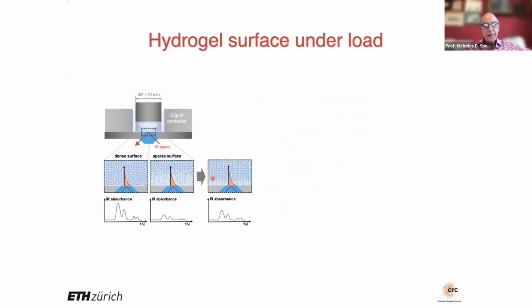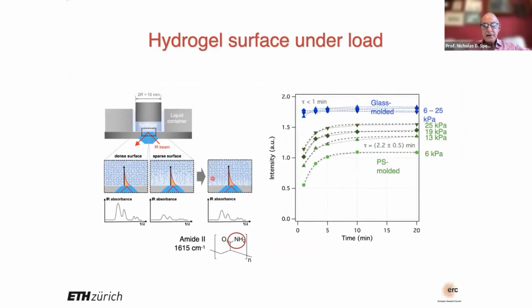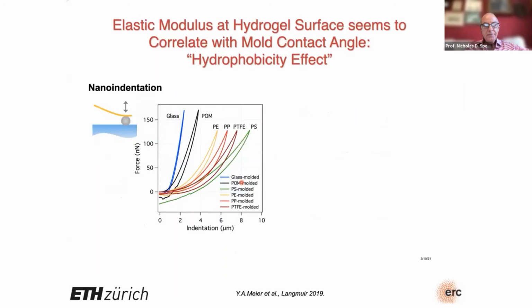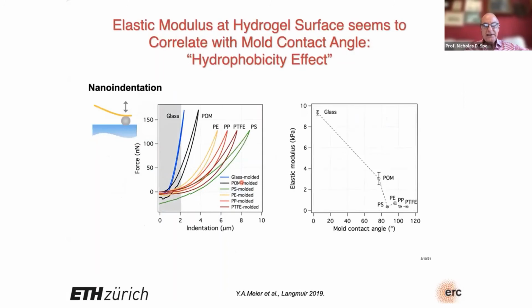Now, there's also a time dependence. On the glass surface, obviously, there's not much time dependence because there's not much change. But the change you see in the case of the dangling chains has a time dependence, a time constant of minutes, due to the slow exudation of the fluid from this rather open region where we have the dangling chains. So that's the elastic modulus. It seems empirically to correlate with the mold contact angle, so with the hydrophobicity.